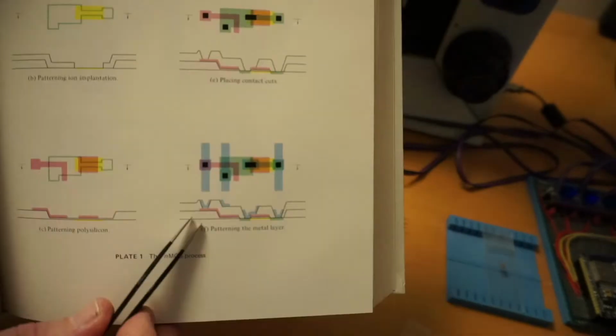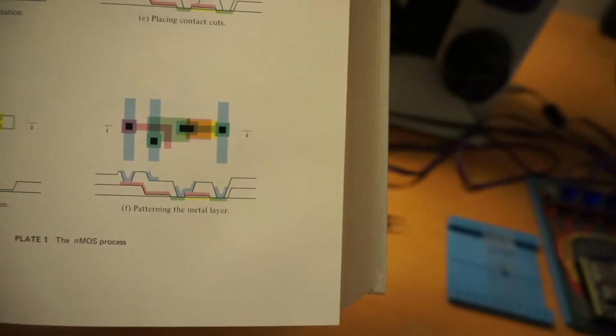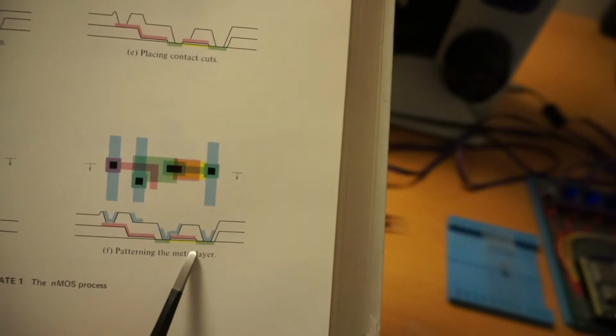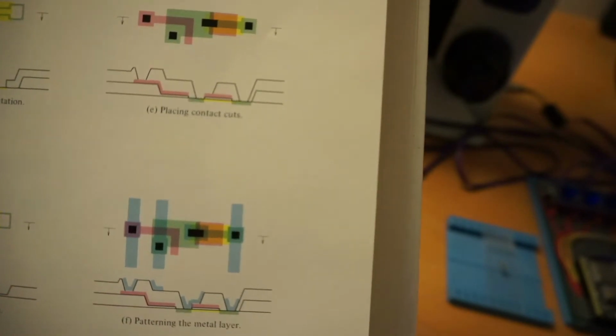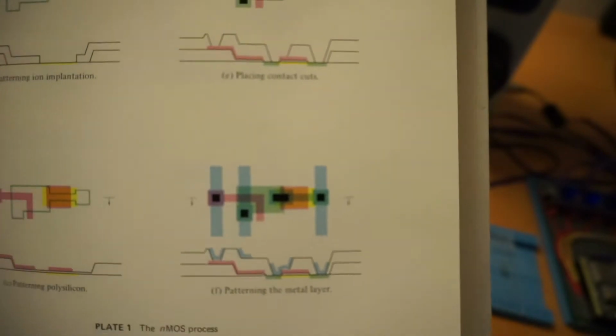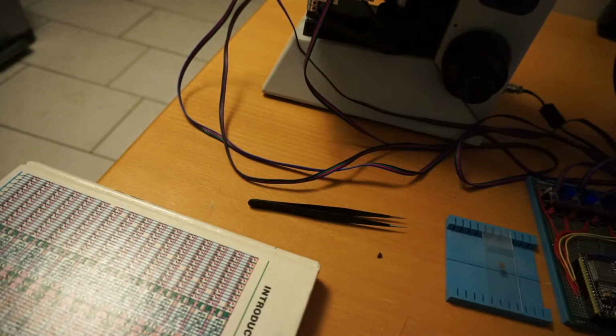But this is the picture I wanted to show. This is basically the type of 3D structure that you end up with. So you will have the substrate at the bottom, which is flat. You will have diffusion areas. You will have polysilicon. You will have more glass areas. You will have metal layers that are all conforming to the glass and polysilicon and everything else that's on here. So it really gets into this interesting 3D type structure. If you start lapping on this, you might not get the expected result because this is a 3D structure like this. Also remember, the thicknesses of these layers is incredibly thin.